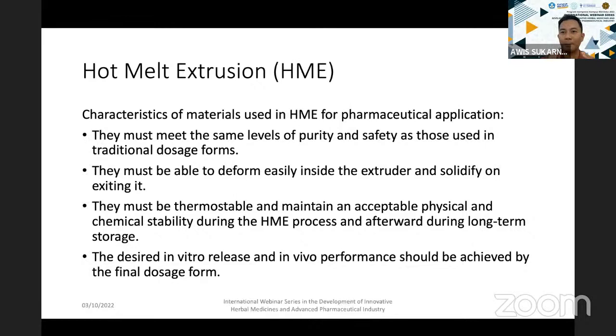Because sometimes when you physically mix these materials, they might show these properties, but when you put them in the hot melt extrusion, they won't show these properties. So that's why for this kind of technique, you need to check before and after the process. It means before, which is the physical mixing, and after you extrude it, does it show the similar properties that you are aiming for?